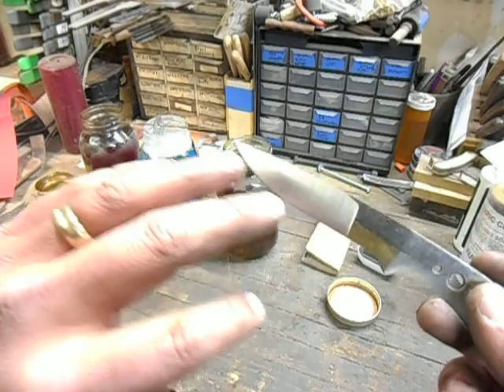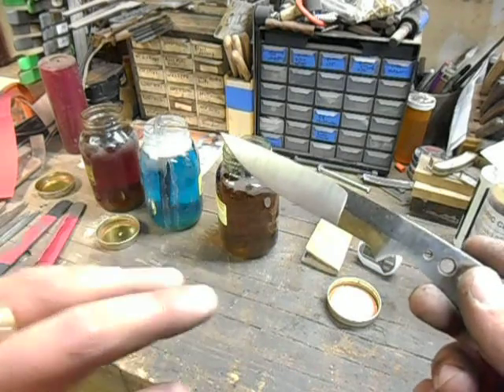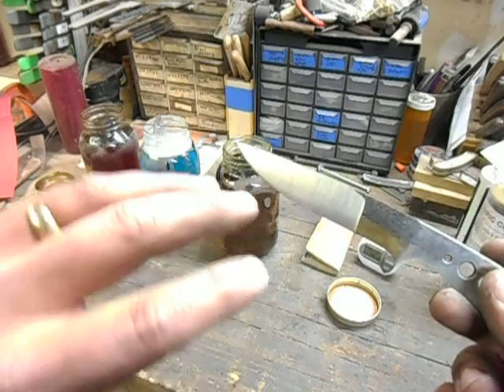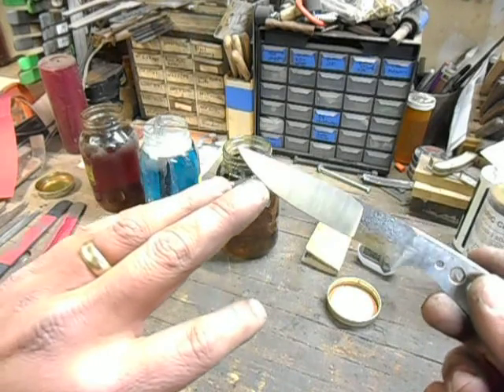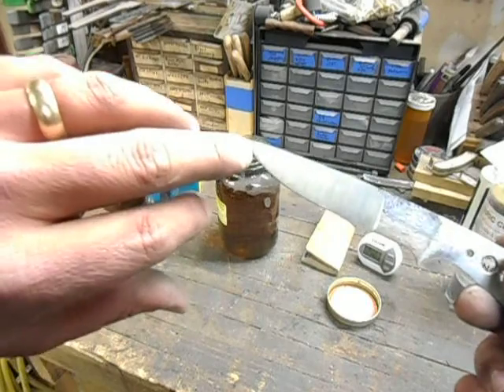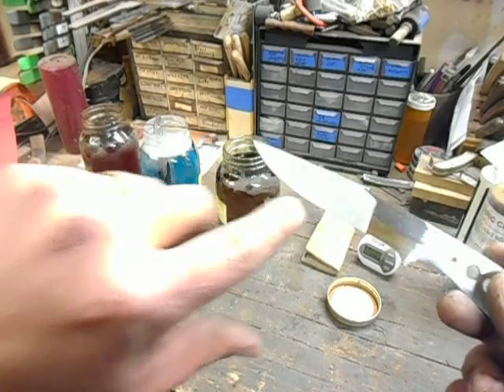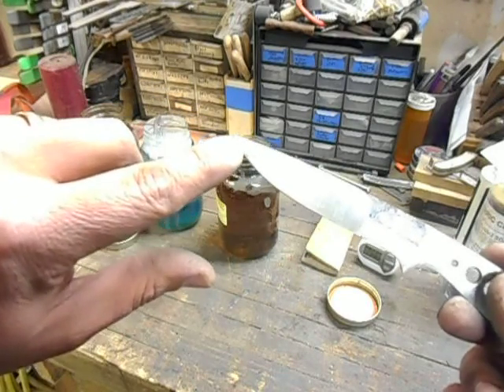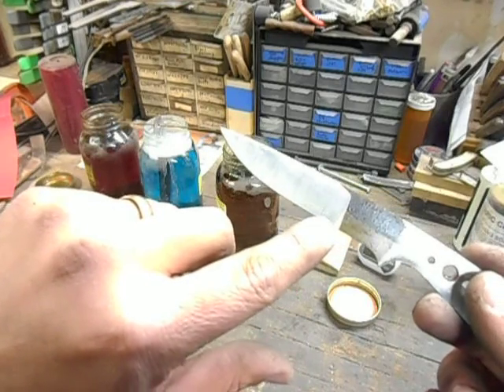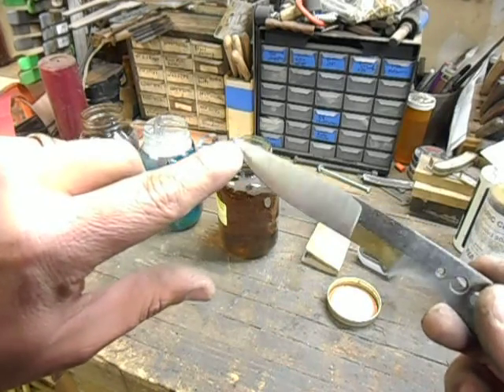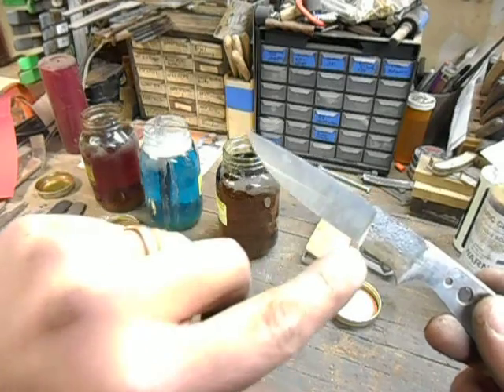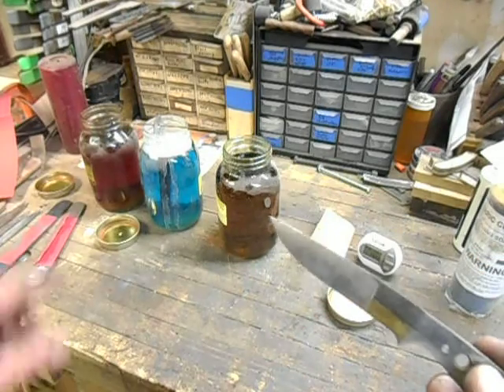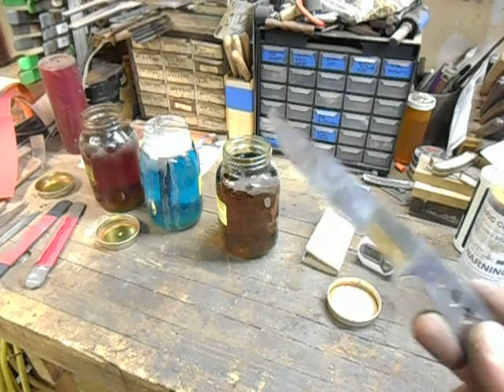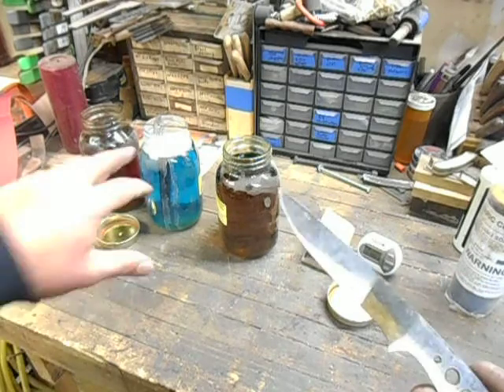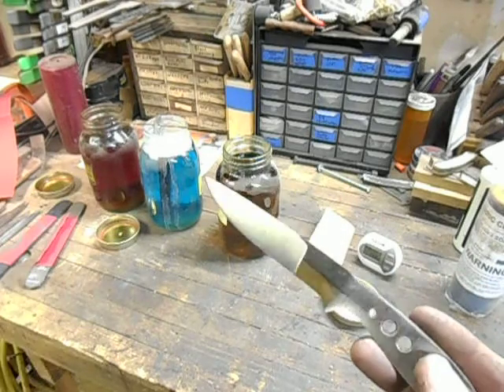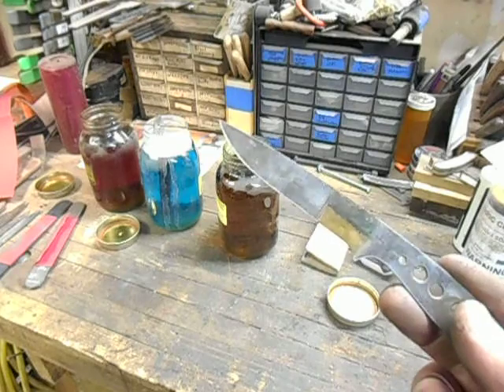And different portions of the blade will act differently in use because you will have a whole bunch of different things going on in there. You might have overheated the tip and not the belly. Well, that tip is going to dull at a faster rate than what the belly will, because the tip has been overheated and the belly was still okay, possibly. Etching a blade can show you that, and we'll get to see that here in a second. This blade, we'll get to see if I overheated the edge or not.